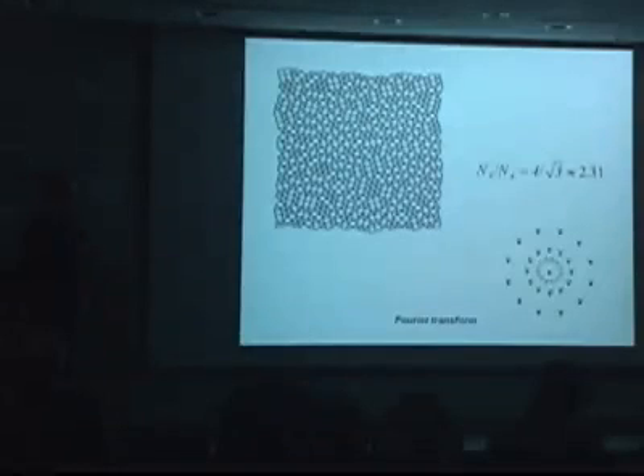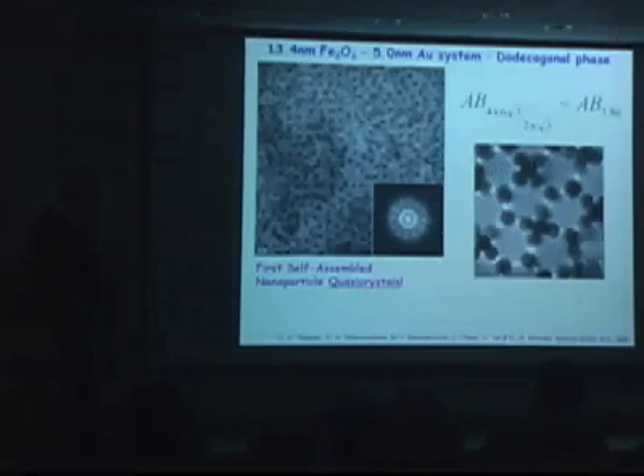That's what will give you irrationality. And also, the second requirement to build this fancy structure: you can swap tiles until you approach the maximum of entropy. It's the most possible, the most disordered tiling under conditions of equal areas. So, that's what probably drives the self-assembly process.